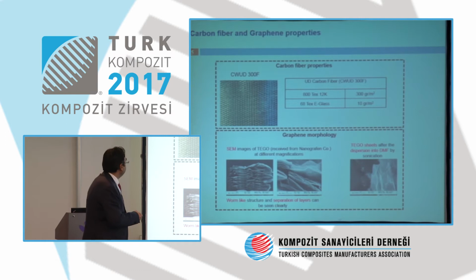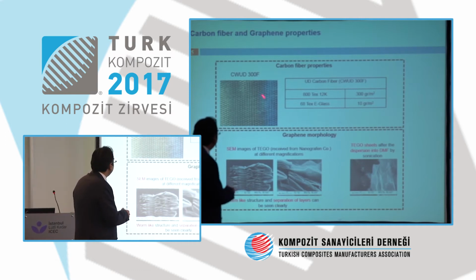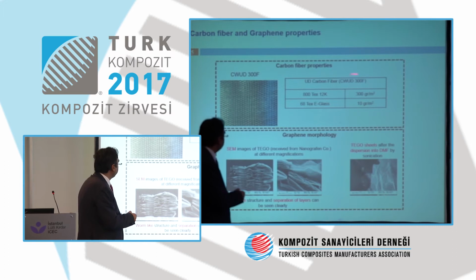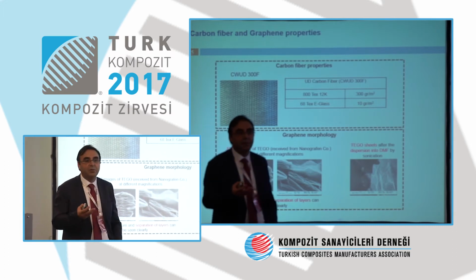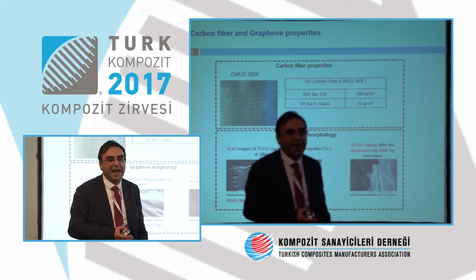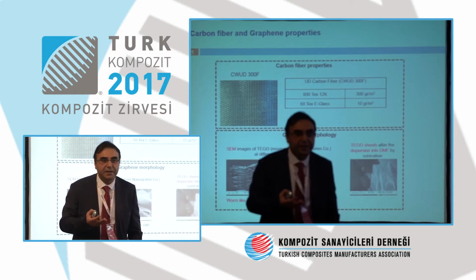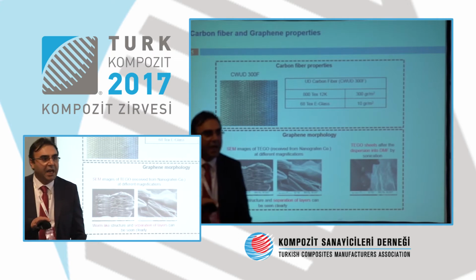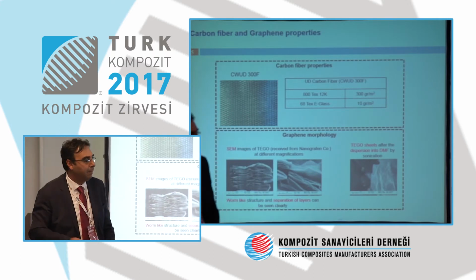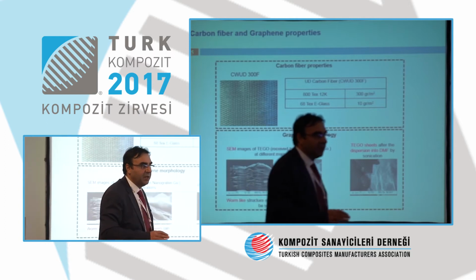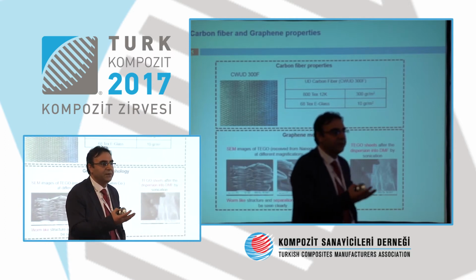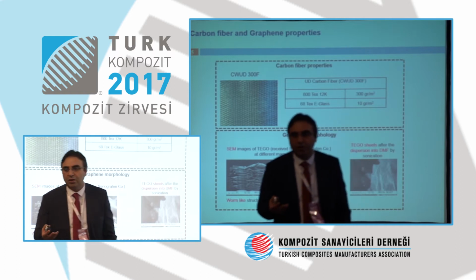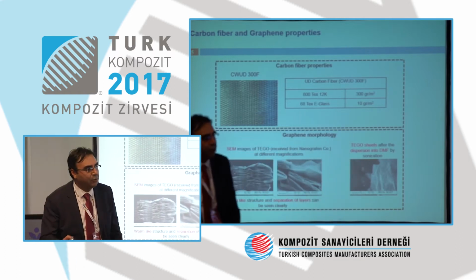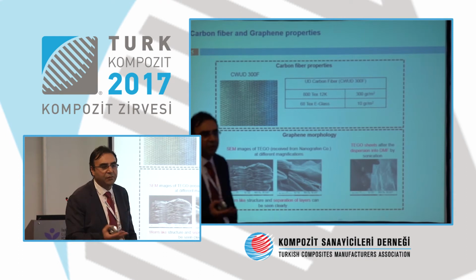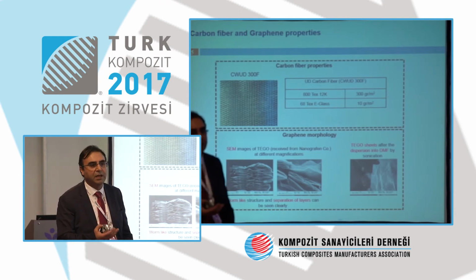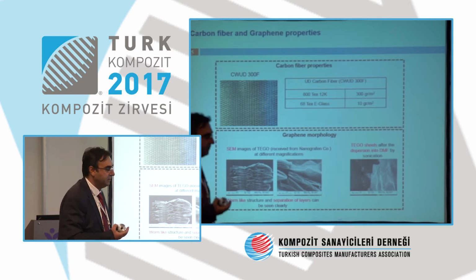And what we have done is that we start with the carbon fiber here, and these are the properties of carbon fiber. And we combine the carbon fiber with graphene, not mixing it in an ad hoc manner. So we integrate it onto the fabric and also onto the resin material. But of course, it is not a mere integration. The surface needs to be functionalized so that your graphene is going to communicate with your carbon fiber and the epoxy by forming covalent bonding. It's not going to be only a mechanical joining process.